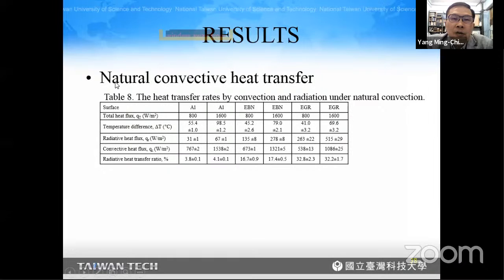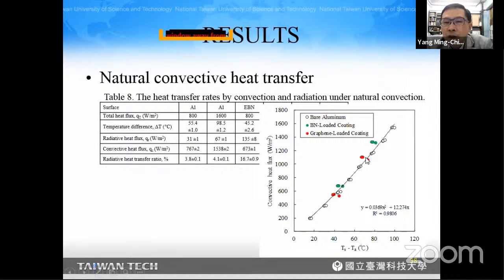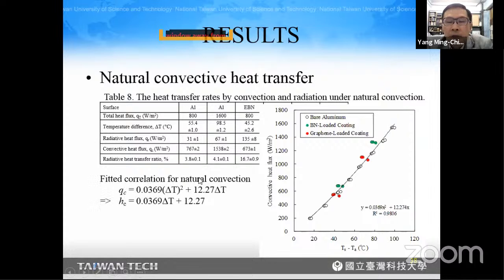Now let's turn to the natural convective heat transfer. And here we have this result: with the graphene loaded coating, the radiative heat transfer ratio increased from 3.8 to 32.8%. So this indicated that the graphene coating can increase radiative heat transfer. And this figure shows that we use a linear regression to obtain a fitted correlation for natural convection. From this correlation, we can calculate the heat transfer coefficient as a function of temperature difference.